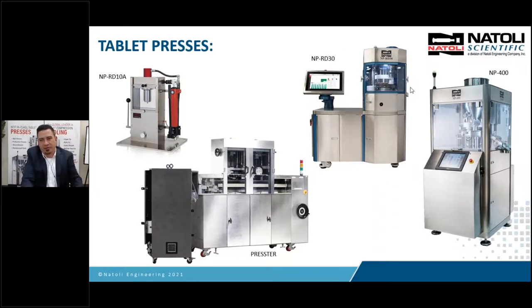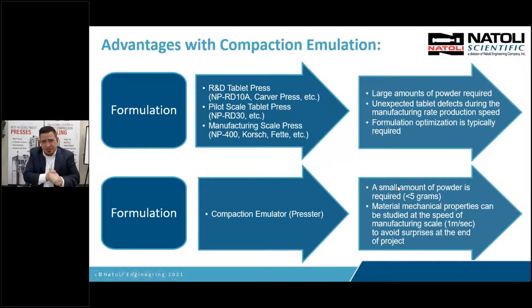So then we go to the RD30, which is our rotary lab scale machine, which can also be used for pilot scale. But this machine was specifically designed for scale-up. So you can use limited amount of material, but you can get up to over 1 meter per second on that velocity. So you can run trials on this RD30 at manufacturing velocities. And then you can go to the production press, which is the NP-400. So the advantages of the compaction emulator, it uses limited amount of material, and it can be compressed at a rate that's representative of manufacturing speeds. You can also measure Heckel plots, work curves, compression data, solid fraction, and so on. So there's a lot of advantages of the emulator, but eventually you need to go to the rotary press process.